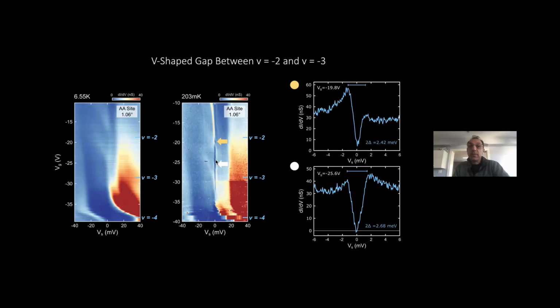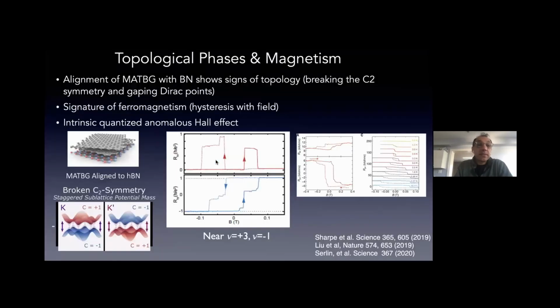So let's see, I have another 5 or so minutes, or 10 minutes. So let me switch topics and connect with Dimitri's discussion about topological phases and magnetism in this system. As he pointed out, some beautiful work by David Goldhaber-Gordon and Andrea Young showed us that when we have this magic angle twisted bilayer graphene aligned with the boron nitride underneath, the system begins to show magnetism, and it shows signatures of intrinsic quantum anomalous Hall effect, which is basically the system showing you a quantized Hall conductance at 0 magnetic field.